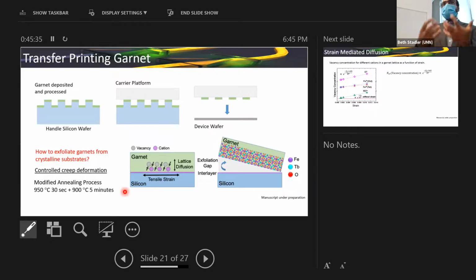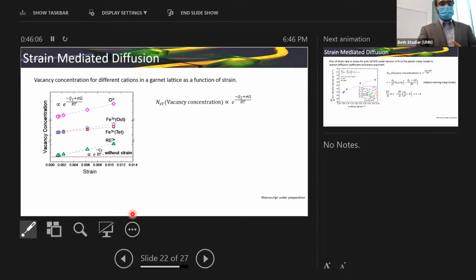Now, what we do is we take this concept and functionalize it to our particular scenario. We deposit garnet on a silicon substrate, and by itself it has a tensile strain at the interface. By annealing it at a specific recipe, which I have listed down here, we are able to facilitate a diffusion of vacancies away from the interface, such that it creates an exfoliation gap a couple of nanometers into the film, and that can be exfoliated quite conveniently by using Scotch tape.